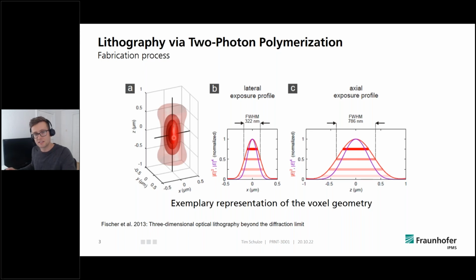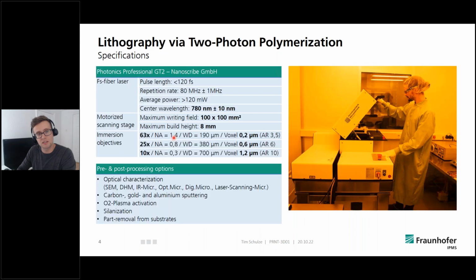The system we are using at our institute was fabricated by the company Nanoscribe, and the system is called Photonic Professional. I want to go over the specifics real quick so you have a rough idea of the capability. Like I said, it irradiates the negative resist with infrared radiation, and we have a maximum writing field of approximately 100 by 100 millimeters, so 10 by 10 centimeters. So we're able to build really wide structures, even in the centimeter domain, although the height is limited, in this case to approximately 8 millimeters.